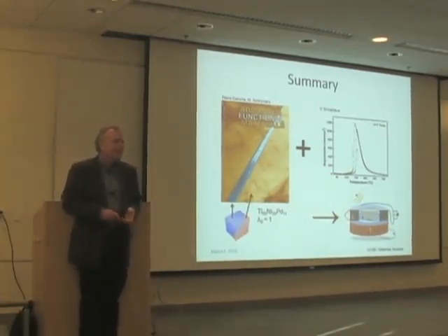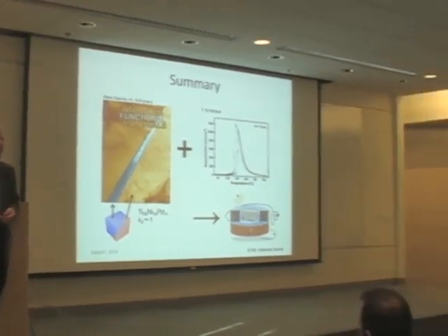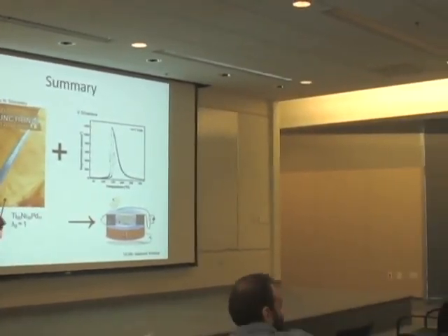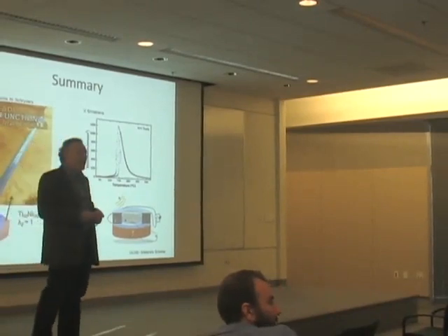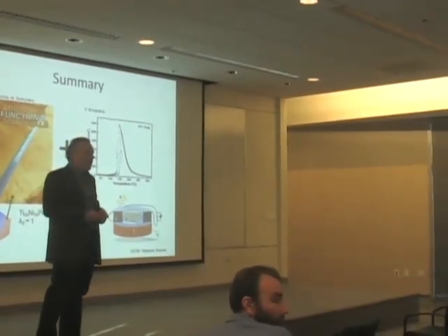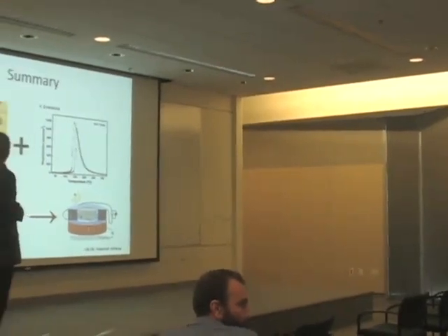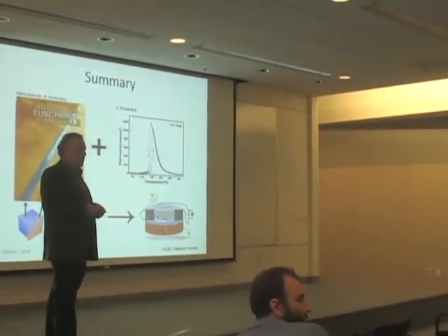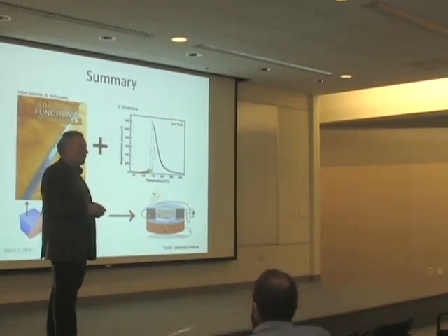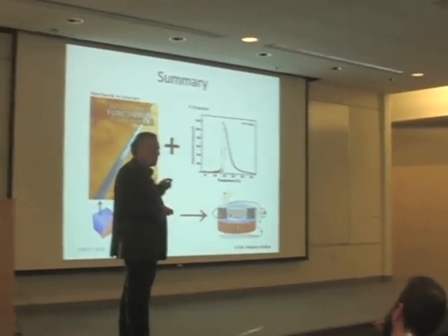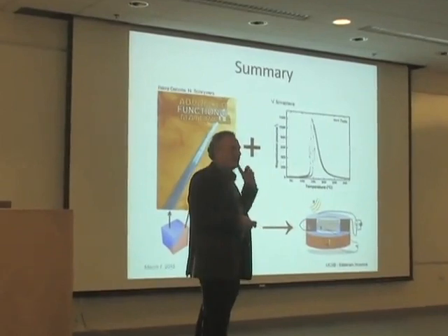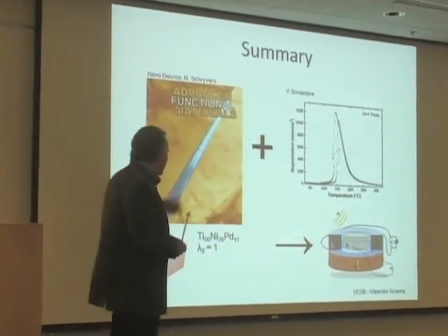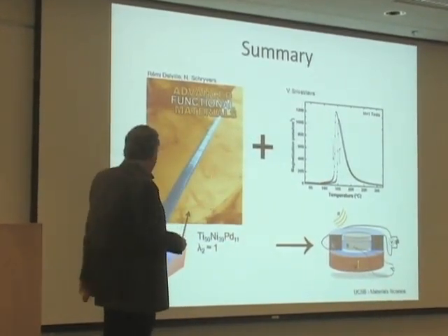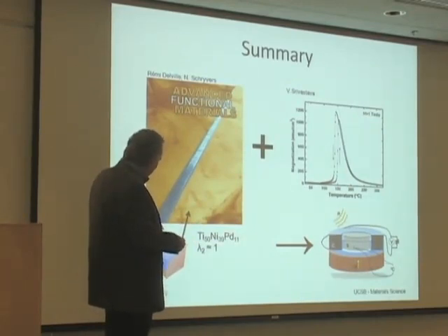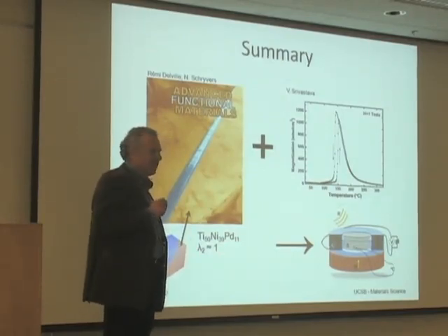So you kept showing the boundaries that look like they were parallel to each other in those alternating phases. Yes. Right, right. They're two different, the earlier picture, they weren't parallel, and here they're not parallel. It's two different reasons. For here, the reason, at least I believe, is that this alloy, as I said earlier, it's really 9.25 that has lambda 2 really equal to 1. I'd have to say a tolerance. But this is not quite lambda 2 equals 1.